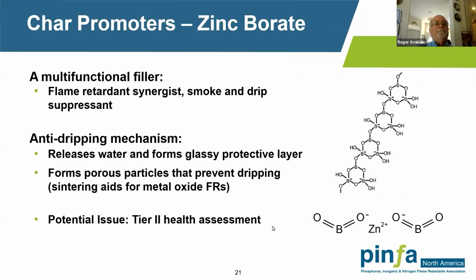Next slide. We talk about other char promoters like zinc borate. Again, it's a synergist. You don't use zinc borate alone, but typically what the zinc borate will do, it's a flame retardant synergist. It also helps prevent smoke and also works as a drip suppressant. Typically, the mode of action for the zinc borate is the zinc ion itself does work synergistically with phosphorus and nitrogen materials to promote char formation.